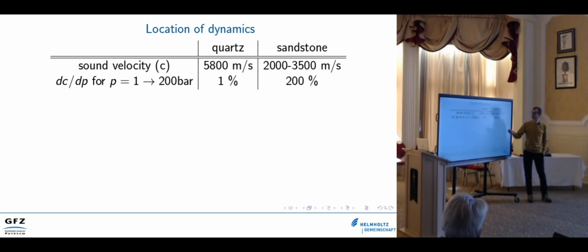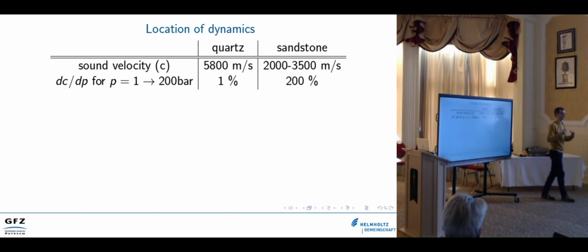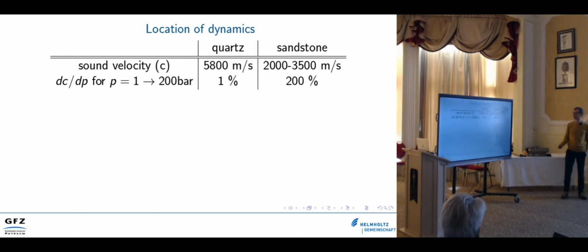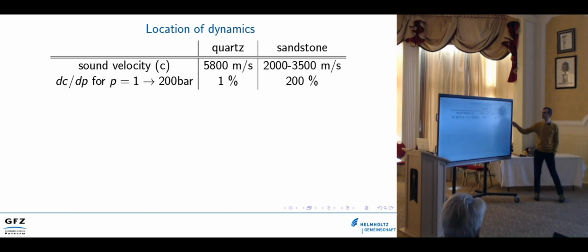And then when we look at the dependence of this sound speed on the pressure, which is the nonlinearity, in fact, quartz, when we compress it from 1 to 200 bars, the velocities change by about 1%. So it is nonlinear, but it has a very small nonlinearity. While when you compress a sandstone to that pressure, you can actually double the velocity. So it depends much more strongly on the external pressure, and the nonlinearity is much, much larger.